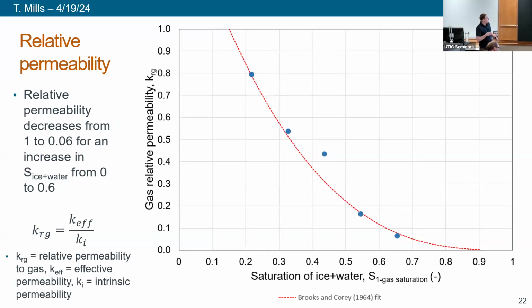And so we can also plot the relative permeability of these samples. If you remember, our relative permeability is the effective permeability, or what we measure, divided by the permeability of our sample at a 0 saturation. And so this plot to the right is showing our relative permeability on our y-axis and our saturation of ice on the x-axis. And we can see that our sample goes from relative permeability of 1 all the way down to about 0.06 with an ice saturation of about 65%. And so we can also fit this line with a Brooks and Corey fit of relative permeability, and we can model this data. This has been really exciting recently to get this data, and essentially this data will be used to inform our modeling effort.